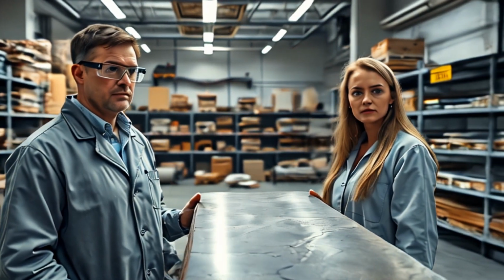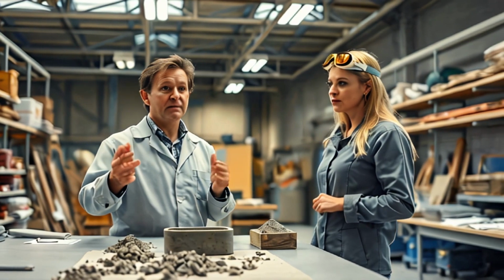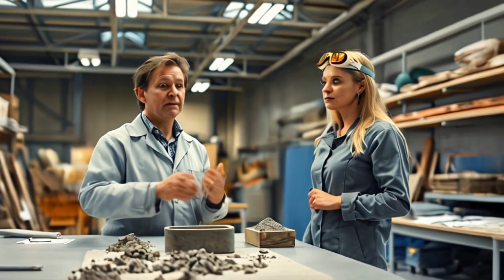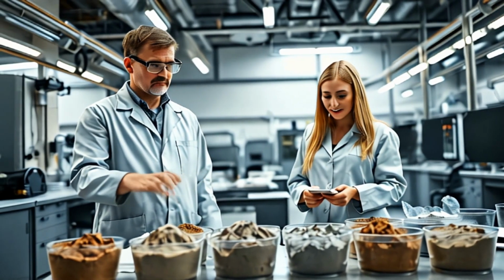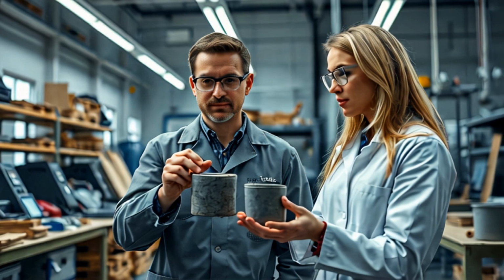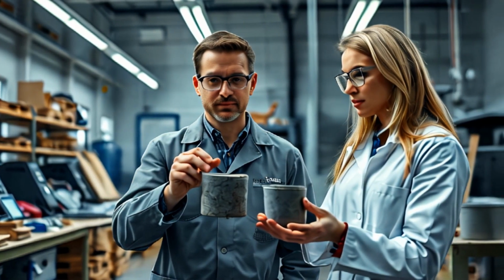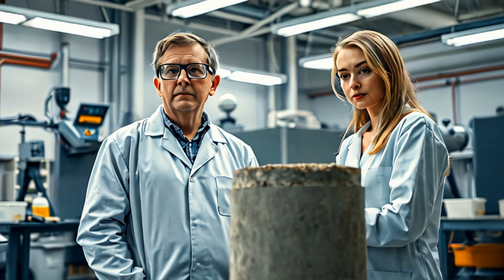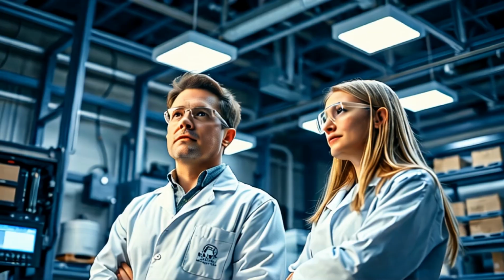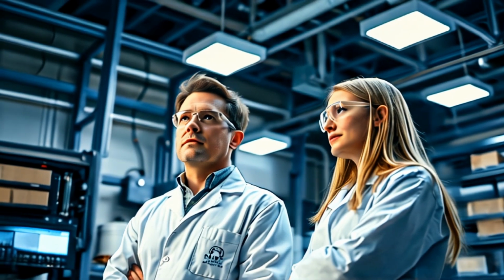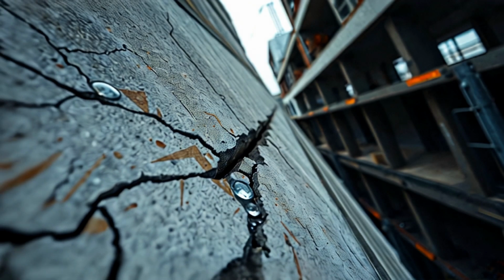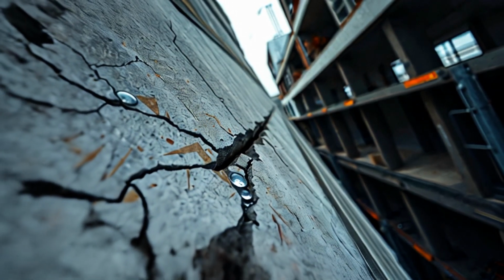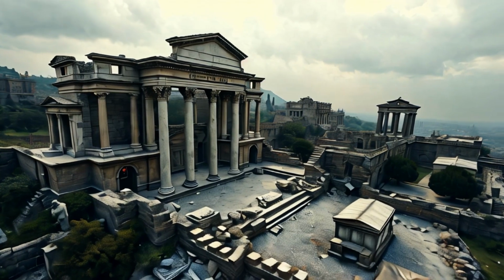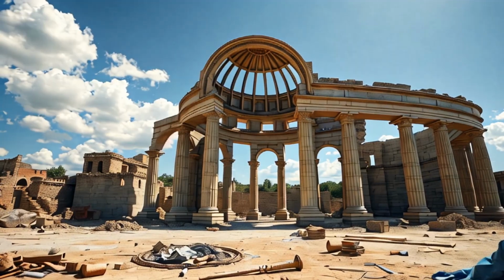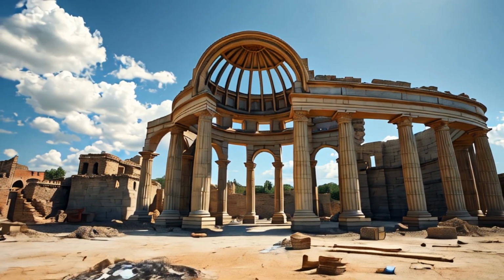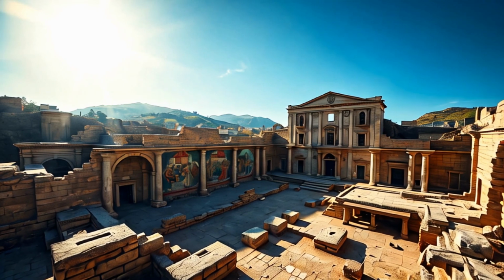In contrast, modern concrete, when exposed to seawater, tends to suffer from chloride-induced corrosion, weakening the material over time. Roman concrete, on the other hand, became stronger with age due to this ongoing chemical process. 3. Slow hydration and long-term strength gain. Roman concrete's strength didn't just come from initial setting, but from the way it continued to gain strength over time. The chemical reactions in Roman concrete were slower than in modern Portland cement, which means that the material kept hardening and strengthening for centuries. Modern concrete tends to gain strength quickly after curing but can lose durability over time due to cracks, environmental exposure, and chemical degradation.